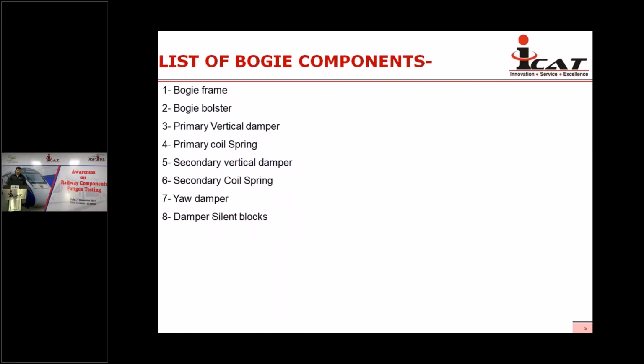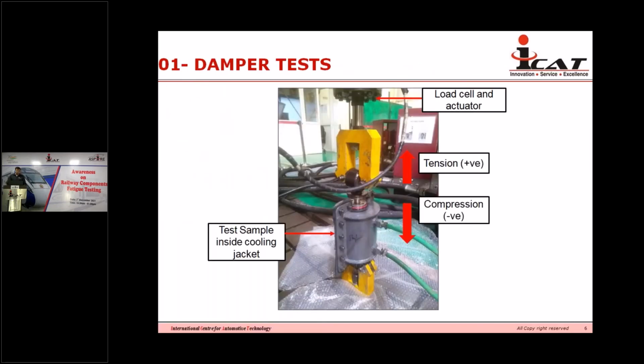One is damper test. The damper test we basically conduct for secondary and primary spring dampers. These dampers are used inside test sample cooling jackets to provide cooling, to avoid any kind of heating during the testing. And we use this whole setup with our servo hydraulic actuators. We prepare fixtures, and then we apply the loading.